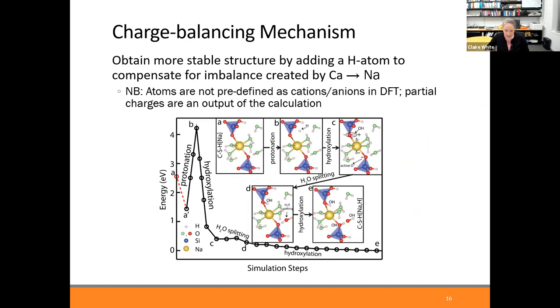was if we bring a hydrogen atom into the system as well, along with the sodium, this leads to a more stable structure compared to just, say, the sodium by itself. And so there's a sequence of events that we saw happening when we placed hydrogen into the system near the sodium. And specifically what happened is this hydrogen formed a hydroxyl with the silicate unit close to the sodium.